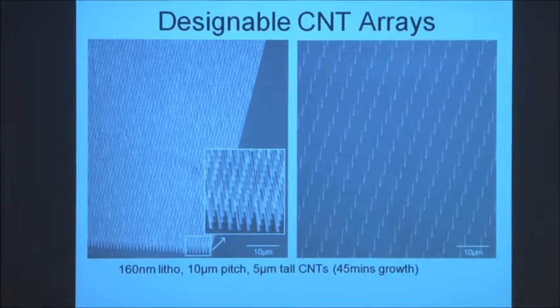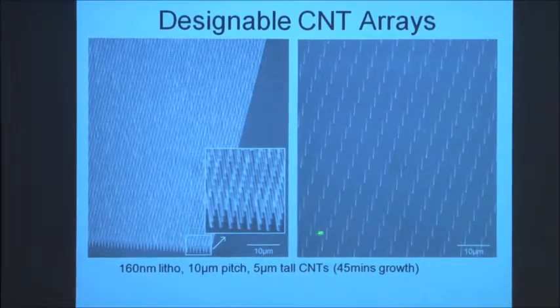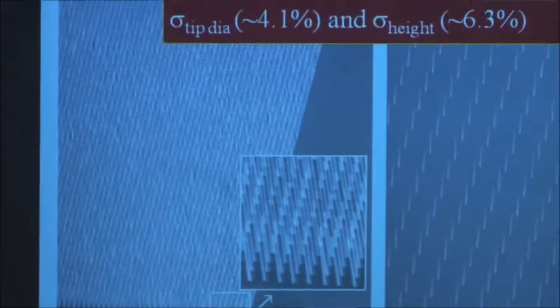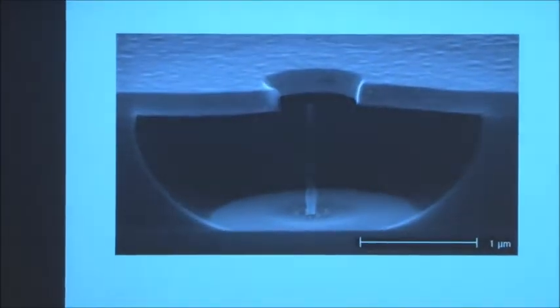If you try and do this for single-wall tubes, by the way, which we've tried, what happens is they all fall over. Because the single-wall tubes are about 1 or 2 nanometers, they just fall down. The only way you can get them to grow up that way is to have them packed close together. So it solves one problem, but not other ones. So anyway, we can now accurately control the height and the diameter and the position. And you can see this is the sigma. It's about 4.1% for the tip diameter and about 6.3% for the height.